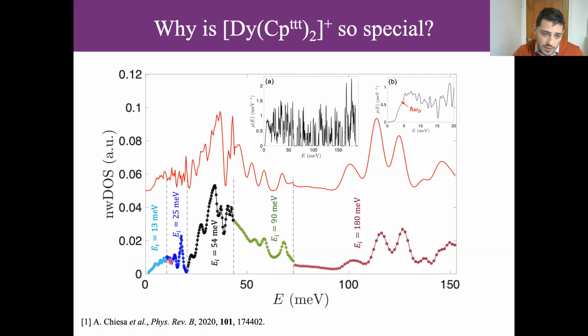And this here is an experimental inelastic neutron scattering experiment where we're measuring the neutron-weighted phonon density of states. And so all these different regions are different incident energies of neutrons, and so we get different resolutions with the experiment. So we have nice sharp peaks down here, and they broaden out from instrumental reasons, not because the actual distributions themselves are any broader.